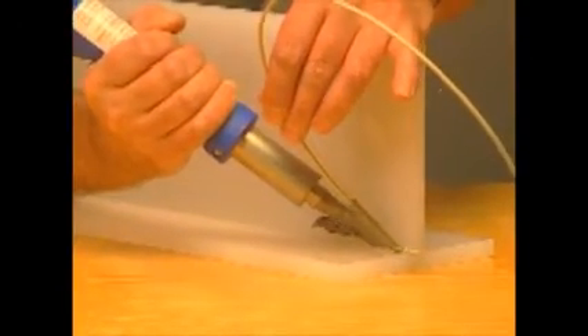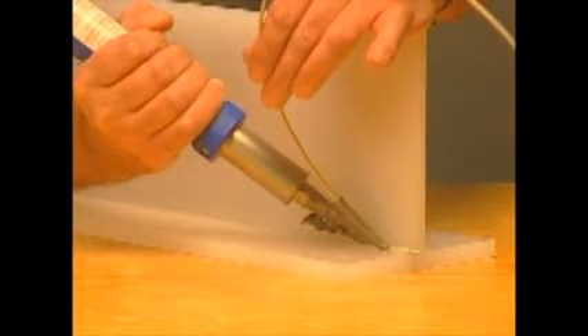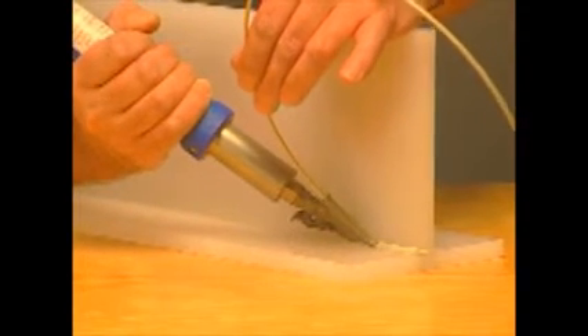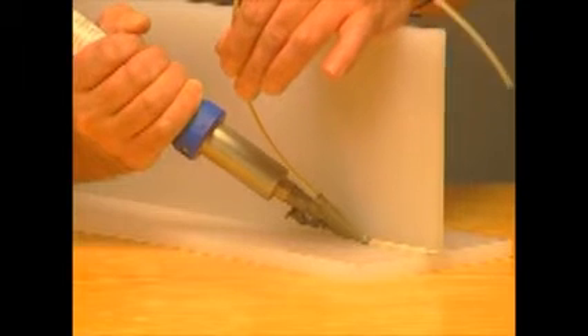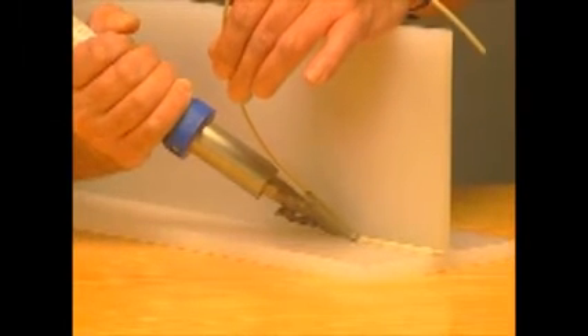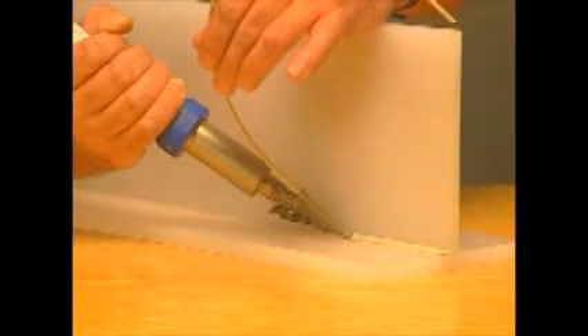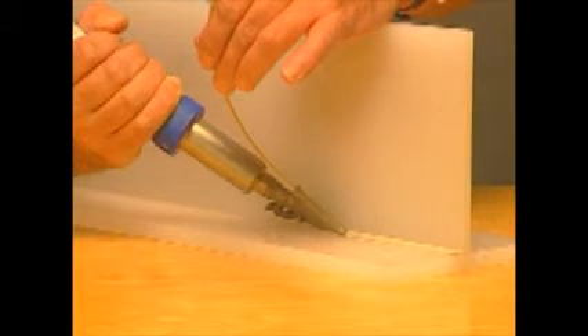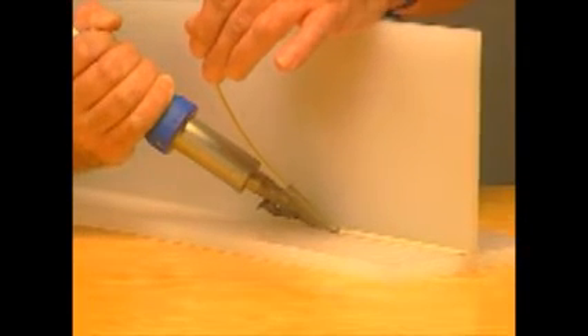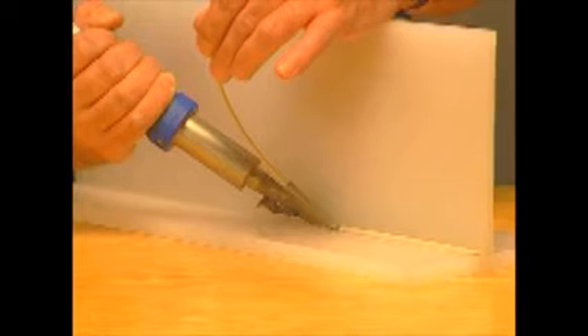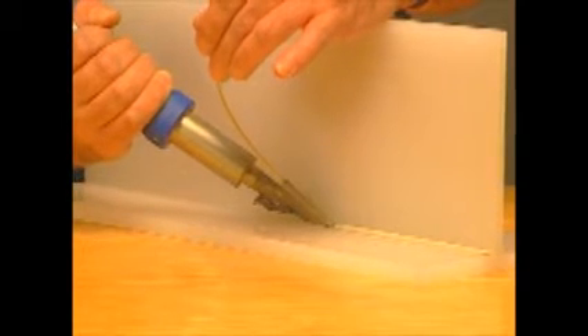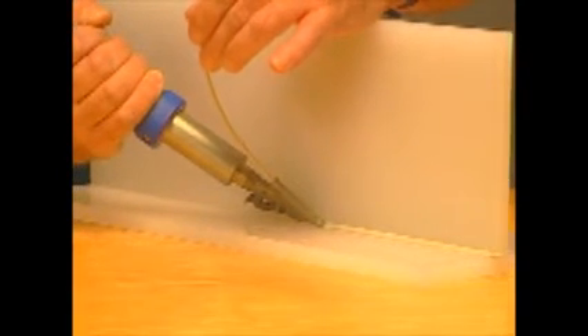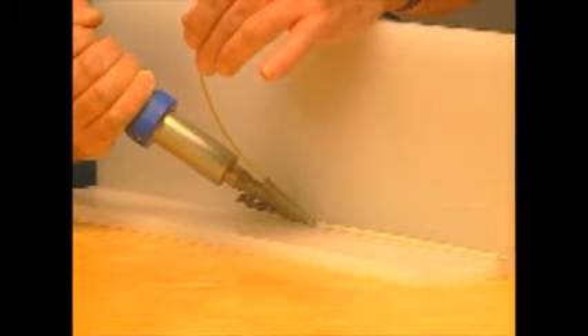Now start the welding process using your free hand to guide the welding rod smoothly through the tip to prevent the welding rod from stretching. Apply the correct pressure consistently while welding at a constant speed. Make sure that the base of the tip is parallel to the weld and that the welder is at the correct angle based upon your weld configuration. In this application, the welder is at a 45-degree angle.